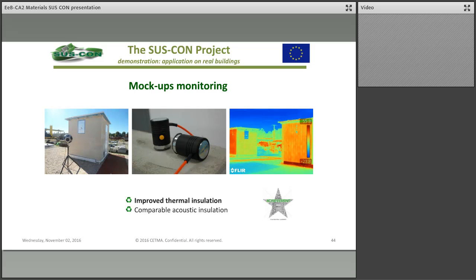We performed some monitoring of the mock-ups in order to evaluate the in-service installation performances of our Suscon products, and we developed some testing procedures in order to evaluate the global thermal efficiency of the new structure, as well as to compare the acoustic insulation of Suscon product with the reference one. And in the end, we were able to verify that Suscon products have improved thermal insulation with respect to the commercially available reference product and comparable acoustic insulation performances.